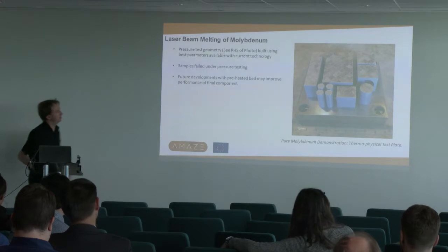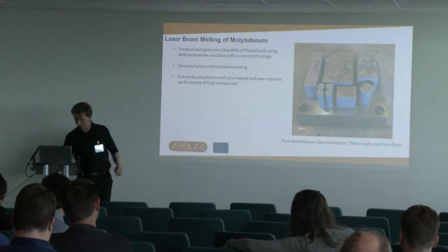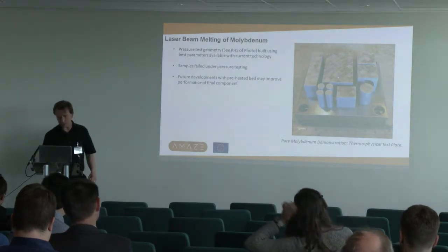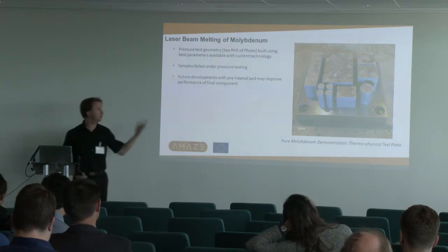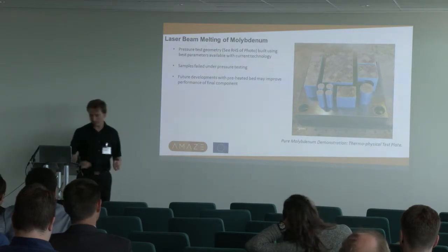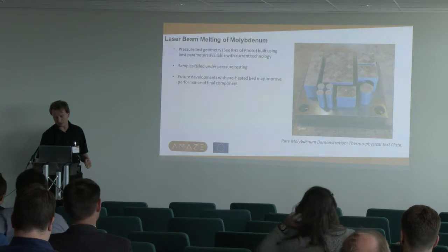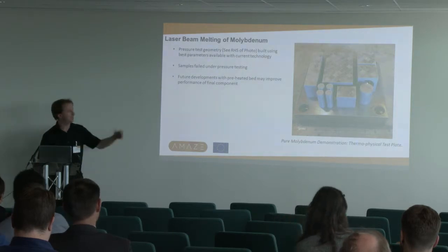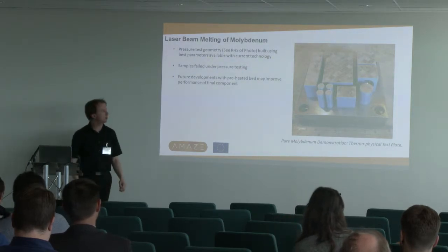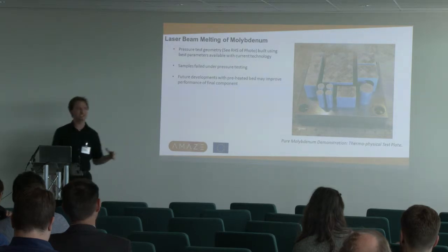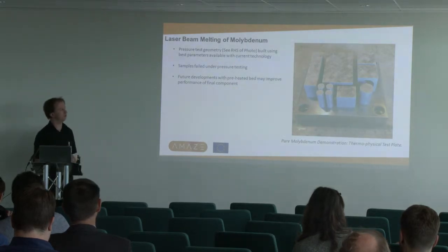So we produced some very simple parts. You can see here is a block with a tube through it, very similar to what Dave showed in copper, but this is in molybdenum. And we produced some of these square, basically just blank end caps that you can braze a pipe onto. These were for pressure testing, just to see if the molybdenum was going to withstand the pressure of the coolant in the high heat flux rig.